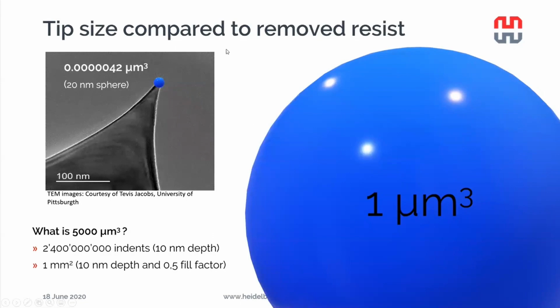Here we have some comparison to the tip size. A small tip size is tiny compared to even a single cubic micrometer. And if you go to 5,000 cubic micrometers, we have a nice image showing that of this ton of 5,000 cubic microns, only a tiny fraction actually stays on the tip and starts to contaminate. And 5,000 cubic microns corresponds to about 2.4 billion of these indents, basically pixels written at 10 nanometer depth, or 1 square millimeter of written area at 10 nanometer depth. So that's quite a lot for such a small tip. And we are still improving, as you've seen in the previous graph.